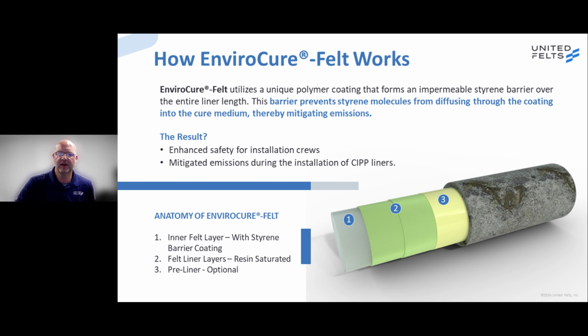How the EnviroCure material works. As I described earlier, this is a multi-component extrusion material, and embedded within the multiple layers is a styrene barrier material. We have a particular polymer that works very well to prevent styrene molecules from diffusing through the coating and into the curing media, thereby mitigating styrene emissions from steam cure as well as water cure.